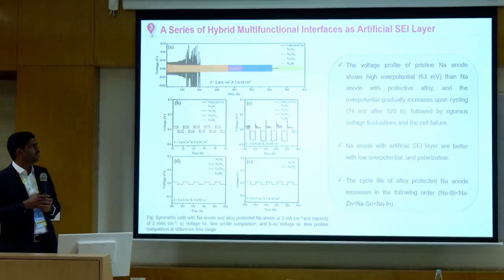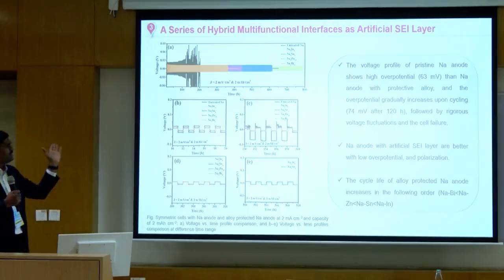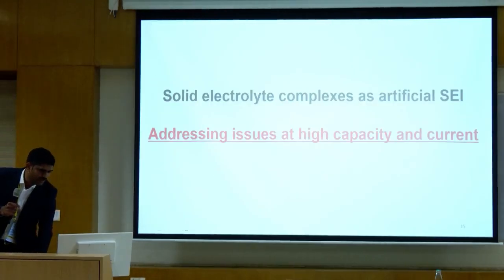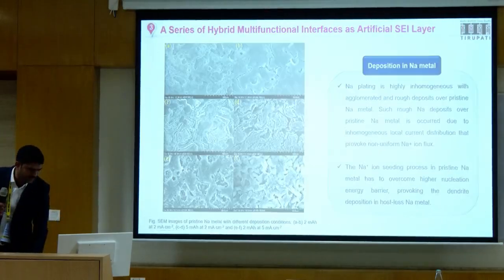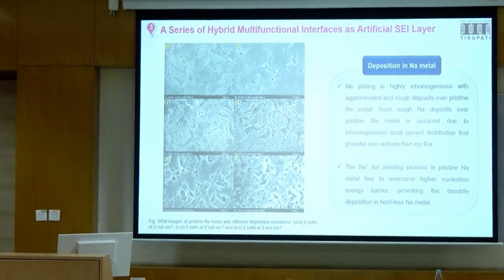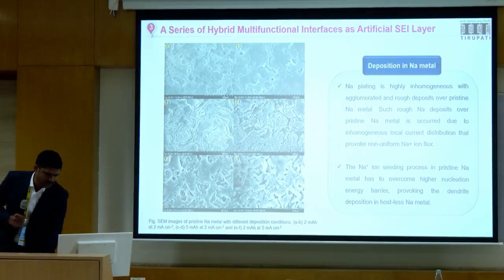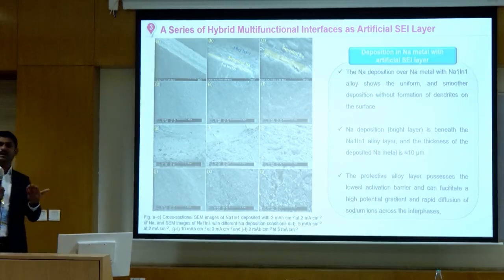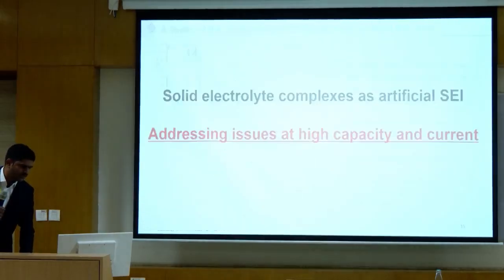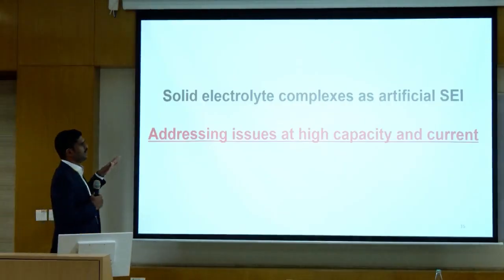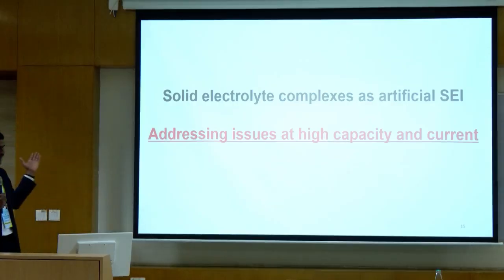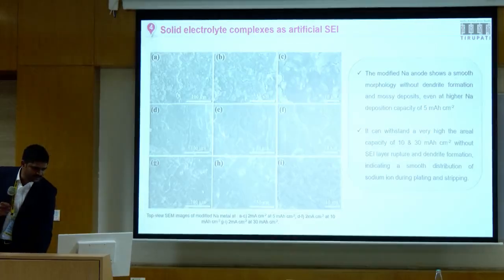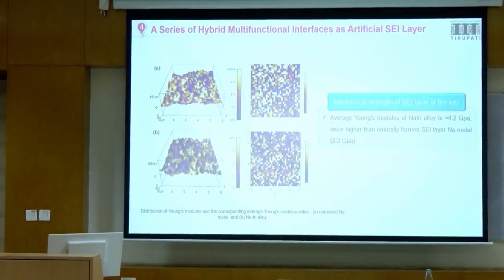You can observe here the black one, that is with the naturally formed SEI layer, but with the artificial SEI layer the batteries can be cycled easily. But we really had issues at high current and capacity. When I want to make a battery with high capacity, say for example 150 Ah or 100 Ah, that's really not possible with the solution we had, or when we want to cycle the battery at higher current density, higher charge rate, that's not possible. So we addressed the issues by replacing the alloy-based artificial SEI layer with solid electrolyte complexes as the SEI layer. What we observed is that the mechanical strength of the SEI layers grown over the metal anodes really impacted how fast the battery can be charged or discharged, and it can really impact the size of the battery we have grown.